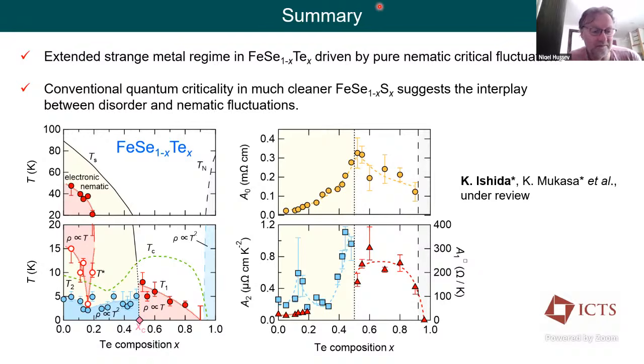There we are. Between 0.5 and 0.8, there is linear resistivity, but T squared for x less than 0.5 and for x greater than 0.9. I mean, is there a kind of Fermi surface reconstruction at xc equal to 0.5 and around x equal to 0.9?